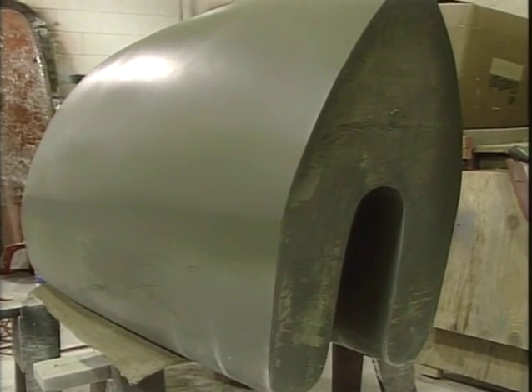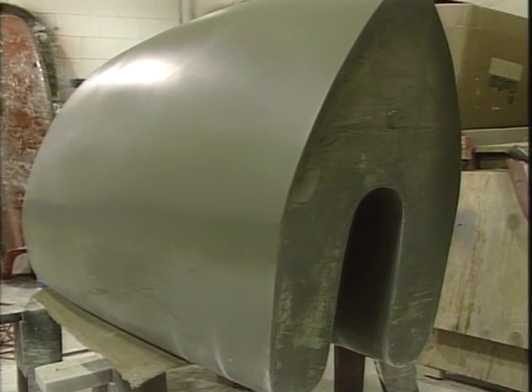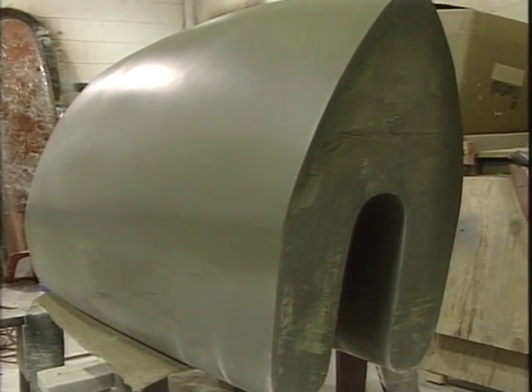The second thing to anticipate is the ultimate layup of parts. Trapped air in the mold or in the parts results from either inadequate saturation or resin and reinforcement pulling away from surfaces that they can barely reach. You want to avoid right angles and tight corners in your design where air pockets can form. As you can see from this later shot of the rear of the plug, I tapered the curves as much as possible to avoid this.